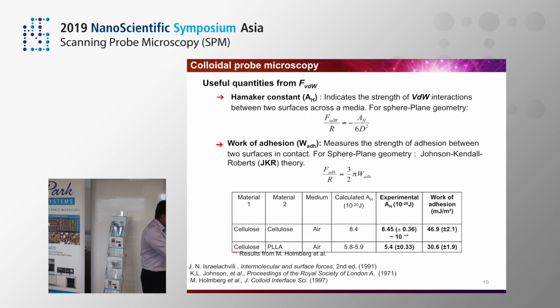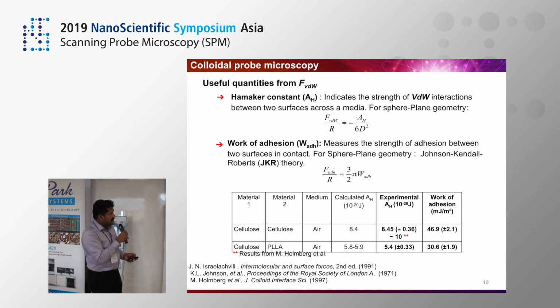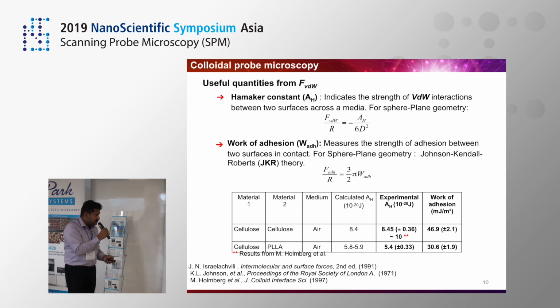And once we have this van der Waals component of adhesion, a useful parameter that we could derive is what is called the Hamaker constant, which indicates the strength of van der Waals interactions between two surfaces across a medium. And for sphere plane geometry, this is the relation. Also, from the adhesion force, we could use the Johnson-Kendall-Roberts theory to measure the work of adhesion. Having this experimental data, we could compare the work of adhesion between cellulose and PLA with cellulose and cellulose, and clearly it shows that cellulose-PLA forms a weak interface in the biocomposite. And any processing parameter should be aimed at increasing this adhesion.